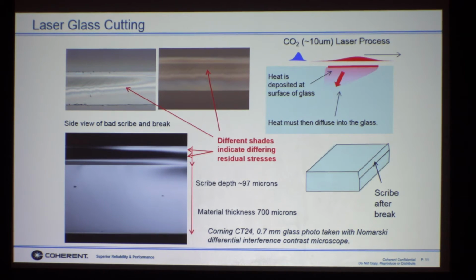The problem with this process is, again, the heat or the laser light is absorbed so strongly on the surface that you can end up having residual stress in the glass. When you create these vents, you want transitional stress to create the vent, and once it's created, you want no residual stress at all. You can see from these pictures, the different shades indicate differing levels of residual stress that have been left in the glass, and most of that is due to this heat damage. And when you have that residual stress in the glass, strength is significantly reduced. These are basically defects in the glass.